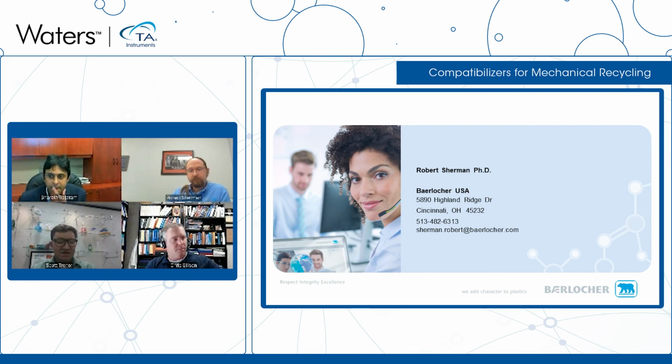Dr. Trenner? Yeah, I'll agree with Professor Ellison. I think especially the linear low density separations are going to be very difficult with any process that exists today. Maybe the high density versus the lower densities you might be able to do. There are some magnetic type separation processes that are being scaled in Europe, and also some eddy current type sortation processes that are being scaled by, I can't remember the name of the company, but they're out of the UK, where you can make finer separations via different densities. So maybe if you're at like a 0.95 or higher high density, you can separate that from a 0.9 low density or linear low. But separating the low and linear lows is going to be continuously challenging.